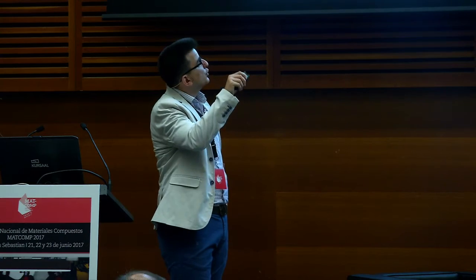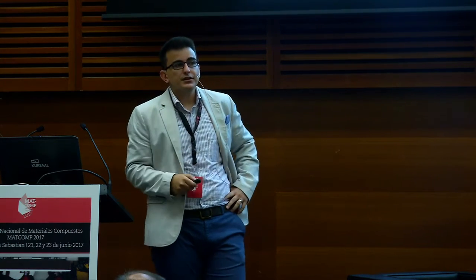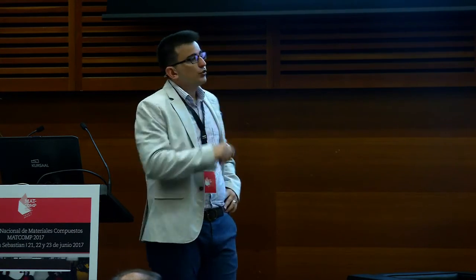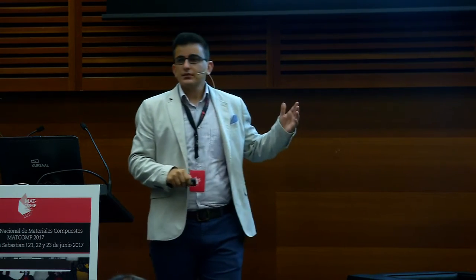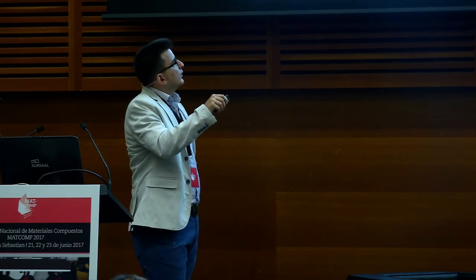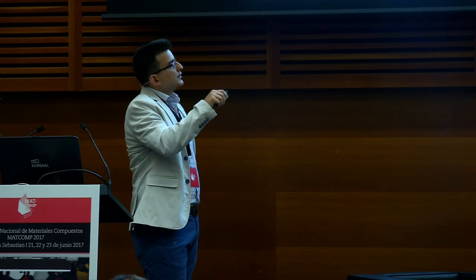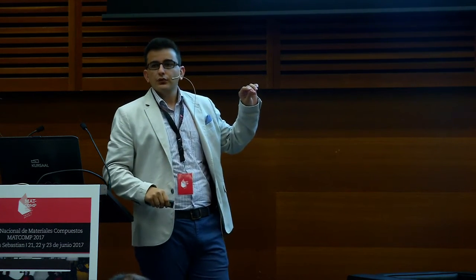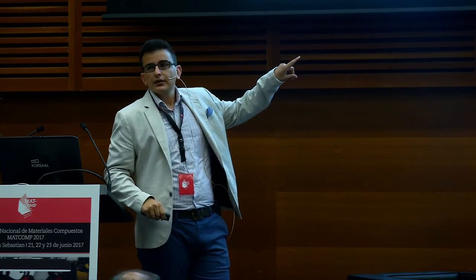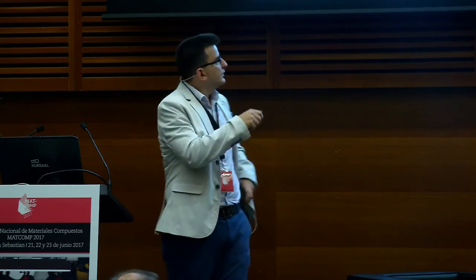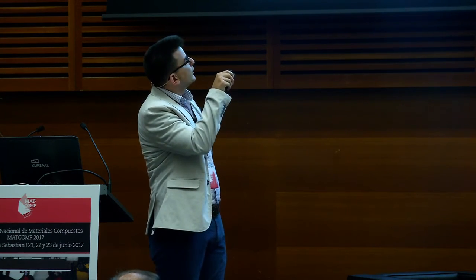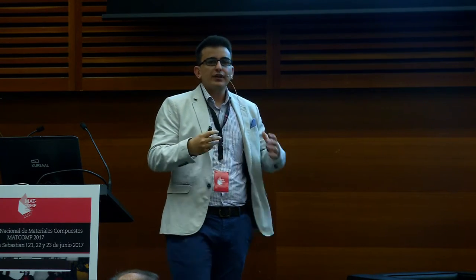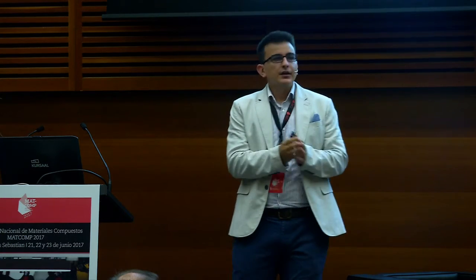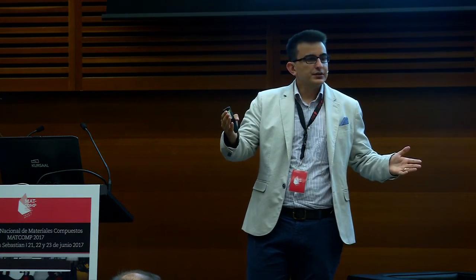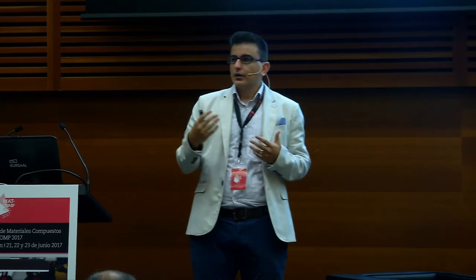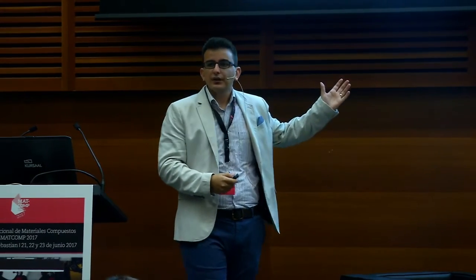And this curve actually is the probability curve of the reference case where we have 200 millimeters per minute for the pulling speed. And let's try to understand the curve. So 0.9 here, this means that the probability of cure degree being smaller than 0.9 is 35% roughly. So we have 35% chance that based on the variations in material properties, we might have a cure degree smaller than 0.9.